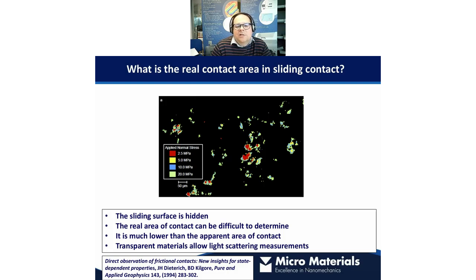So we can see there that you've got regions which are 2.5 megapascals plus. Some regions much, much higher than that, going up to 20 megapascals. So these localized points, when they start to fail, will lead to the onset of a tribological failure at a larger scale.